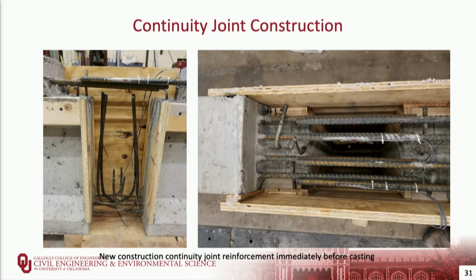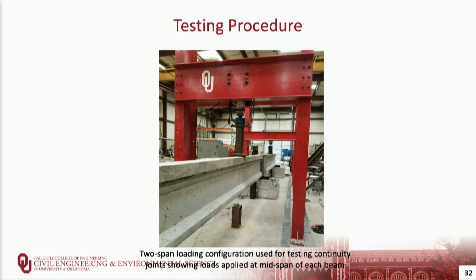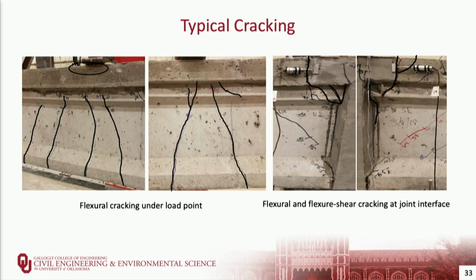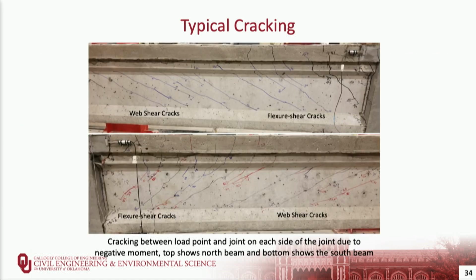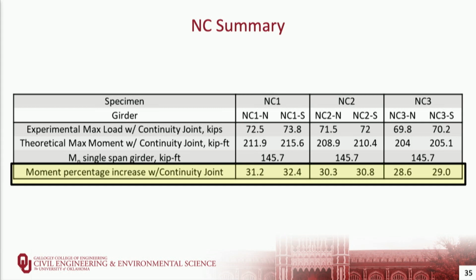So in the first part of our work, we actually looked at building some UHPC connections in the lab, testing them on a 2-span beam system, and looking at the flexural behavior at failure. If we look at cracking in these sections, we see flexural behavior in the girders, we see crushing of the concrete in the girders, and then we saw flexural cracking around the joints, but the strength was controlled primarily by the girders. So to summarize those results, we saw about a 30% increase in load carrying capacity by making those girders continuous.